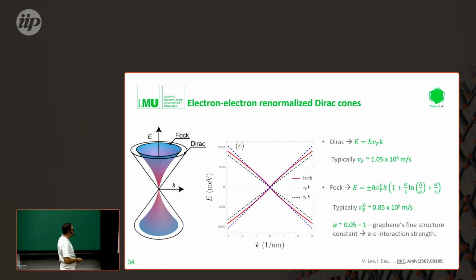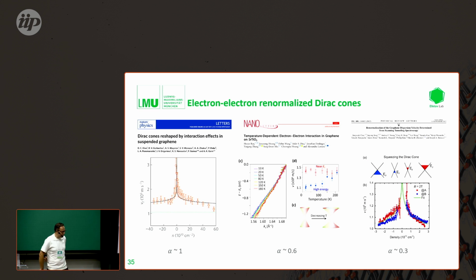This type of correction can be very small. Usually the correction is from a Fermi velocity of 0.85 to a Fermi velocity of 1.05, so really this can be just an effect of 10 to 20 percent. This is the formula which describes it all. It is basically a logarithmic correction onto the linear Dirac dispersion. If one looks back in the literature, this has actually been observed in many places around 2011. The first paper was by Andre Geim, where they did Shubnikov-de Haas oscillations at low temperatures and observed this enhancement. Then Lanzara from Berkeley also observed this correction in ARPES measurements, and also Joe Stroscio and Philip Kim saw it in STM measurements.